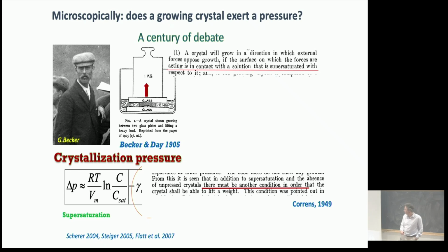However, there's an additional thing that you need to worry about if you think about this experiment or the ice growth, because if you grow a crystal and the crystal simply bridges the gap between the two glass plates, there's no way in which you can add other molecules into that crystal. Yeah, and so the only way in which you can actually exert a pressure is if there's a liquid layer between the glass and the crystal, that gives you new ions to make the crystal grow.